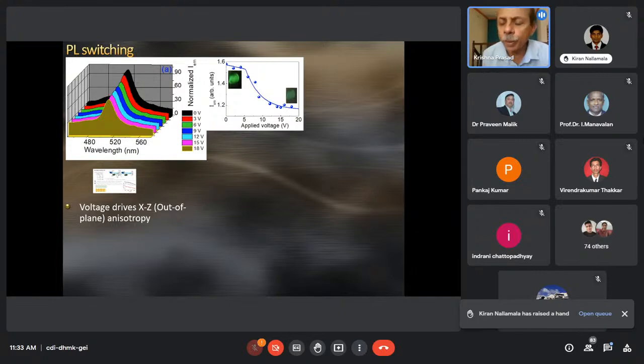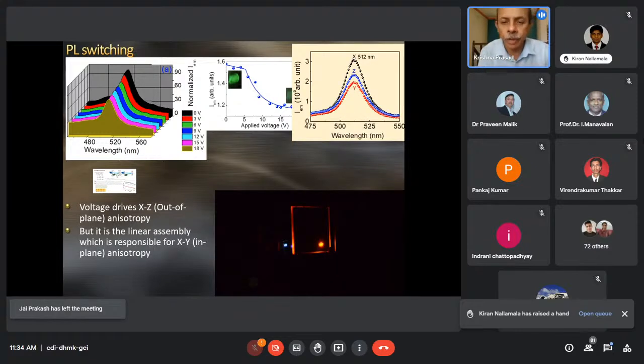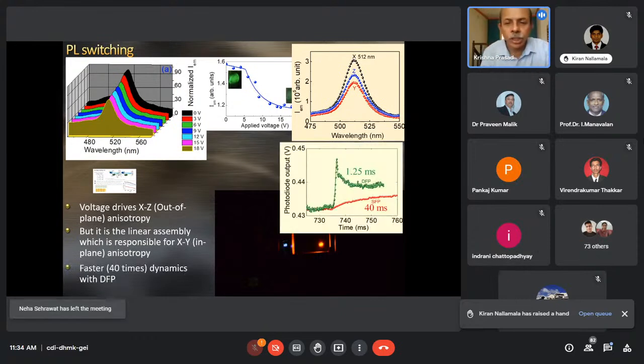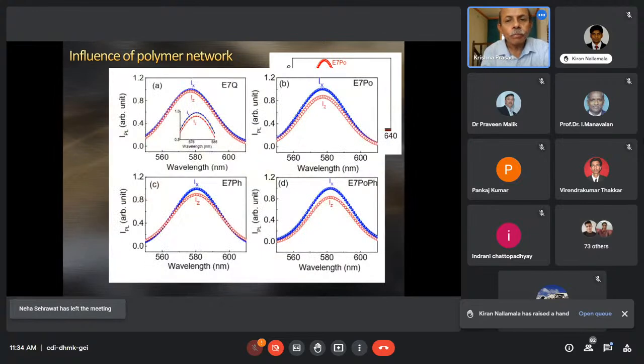These are emissive displays because liquid crystals otherwise are passive devices, and they require a backlight to operate, and that leads to several drawbacks of the liquid crystals themselves. But these are systems which are emissive, and so therefore they could be considered a very potential candidate for future liquid crystal devices. Probably I wanted to show a switching movie here, but I'll skip that and just mention that the polymer network again can enhance the photoluminescence anisotropy in the system. That's what I'm trying to show in these kinds of things.